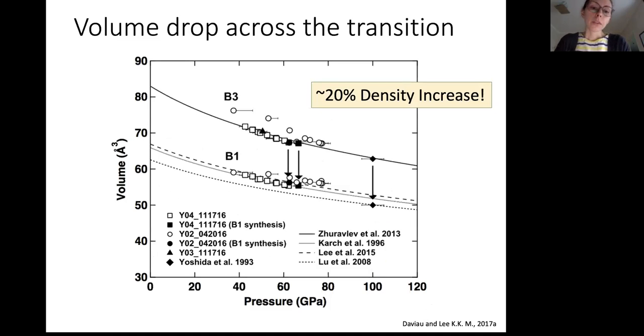Right, so if we plot the pressure versus volume for these phases, at this top line here, this is that B3 ambient pressure zinc blende structure. It has a much larger volume. And then at high pressure with some heat, we have it transition to the B1 rock salt structure, which is a much denser phase. So I want to emphasize this is a 20% density increase across this transition, which is very dramatic, right? And so we're not the first people to have seen this transition. Back in 1993, Yoshida et al. saw this transition at 100 GPa when compressing silicon carbide at room temperature, right?